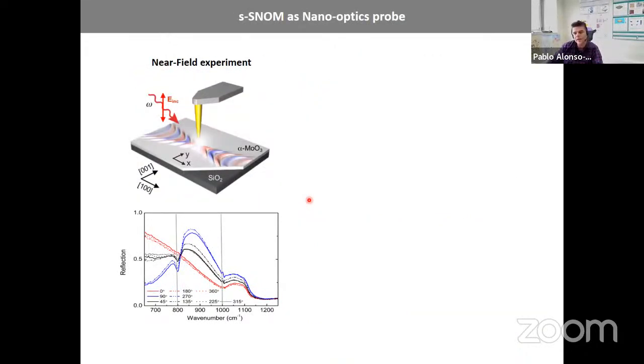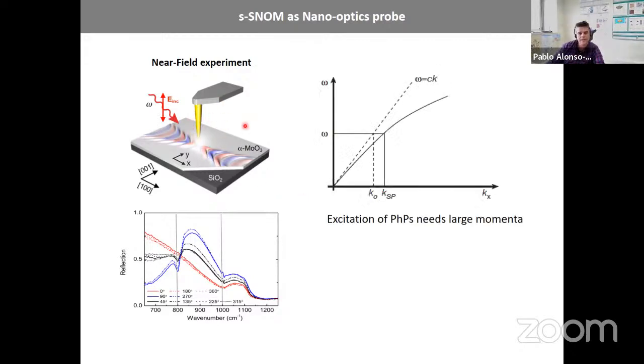So one ingredient is the material, the van der Waals material molybdenum trioxide, but the other ingredient to visualize these phonon polaritons is the microscope that we are using for this. And this is scattering near-field optical microscopy. It's basically an AFM system where the tip is metallic. It is illuminated with far-field light. You remember that the dispersion of polaritons lies to the right of the incident light. So if you just illuminate with free-space propagating light, you cannot excite these surface waves. You need extra momentum. You need to beat this momentum mismatch to launch these waves. And this is the key, because they also have a smaller wavelength.